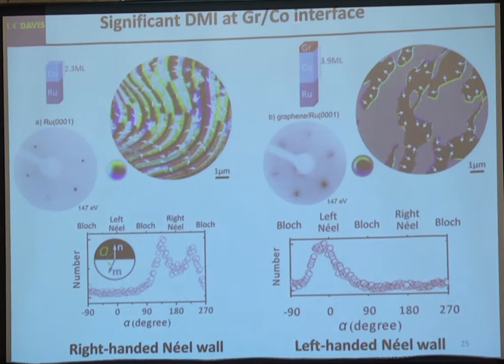However, when we grow graphene on top of ruthenium, we can anneal in the chamber, heating the sample to between 600 and 900 degrees C. You have this nice moiré pattern that indicates the formation of the graphene. And you can grow cobalt on the graphene and heat the sample again. The intercalation of the cobalt will occur, and we have this single crystal high quality graphene cobalt system.